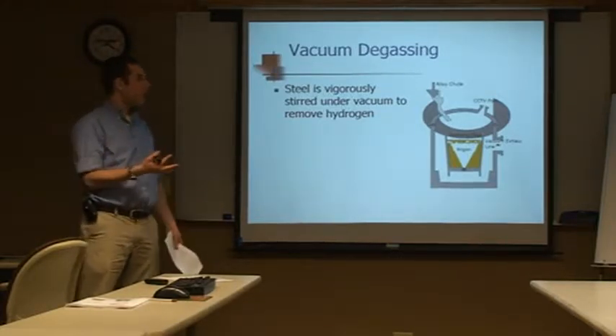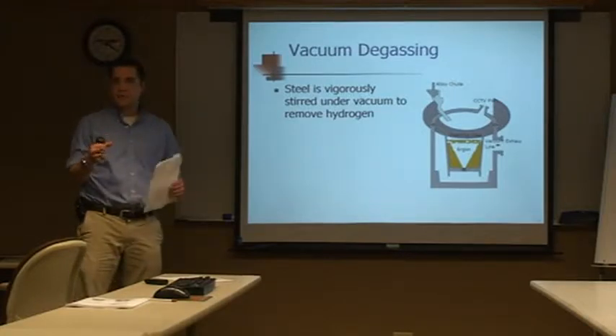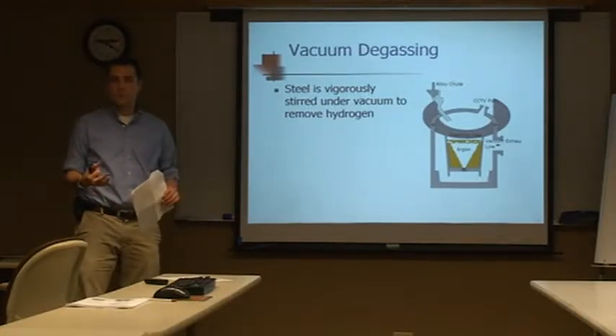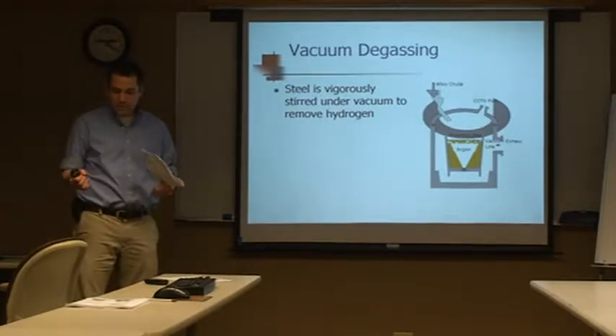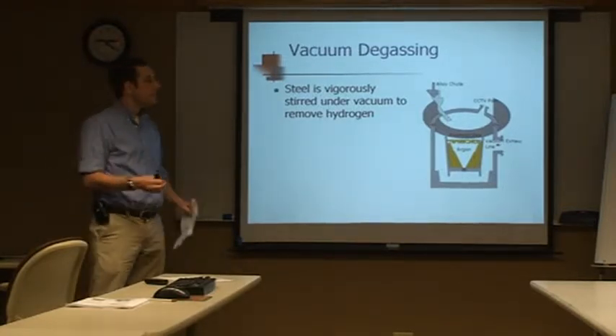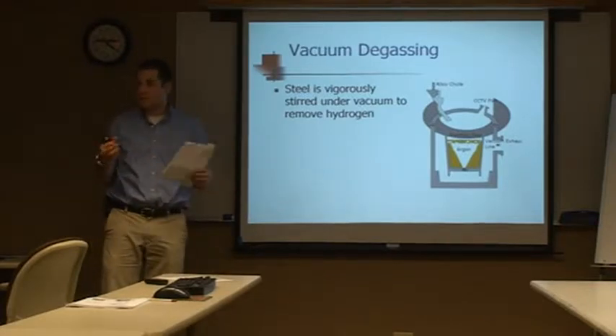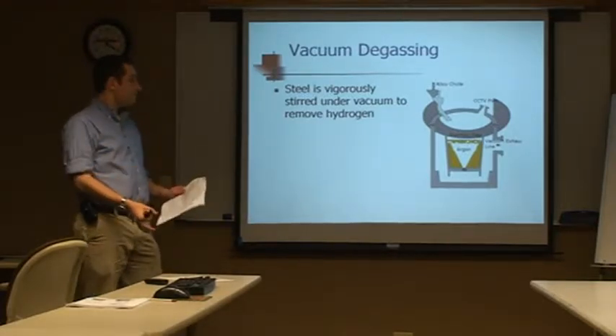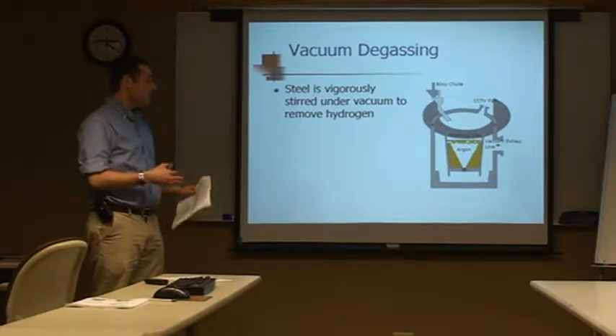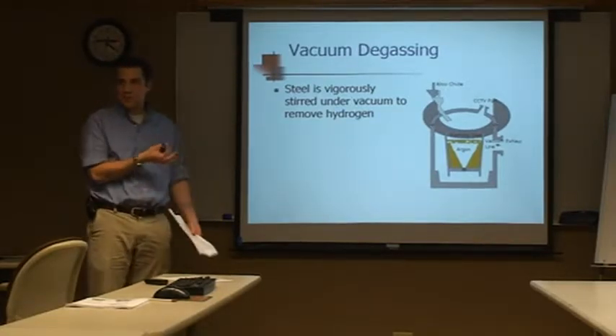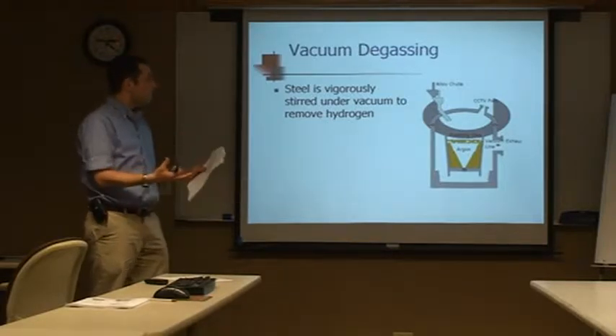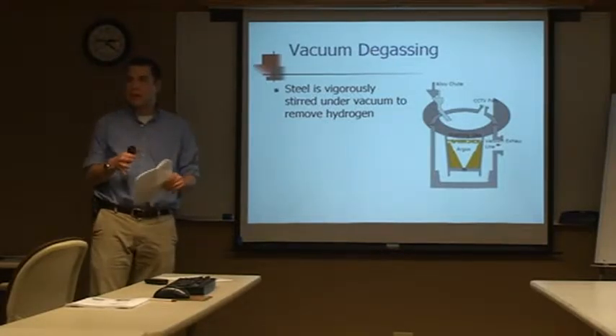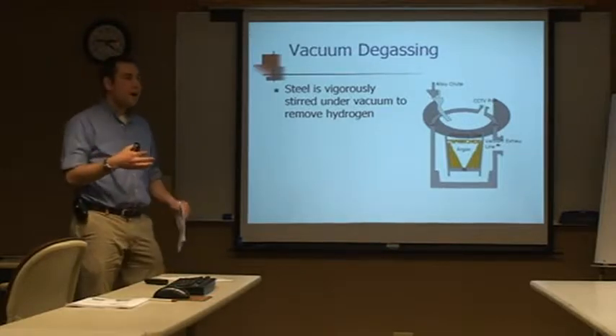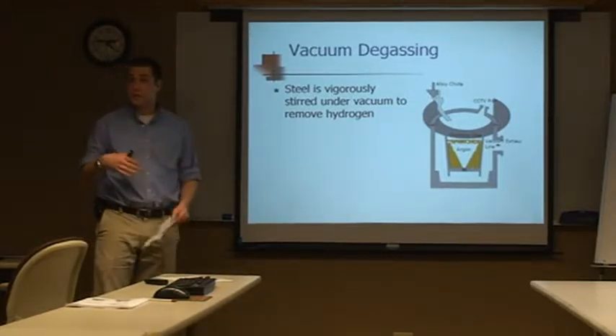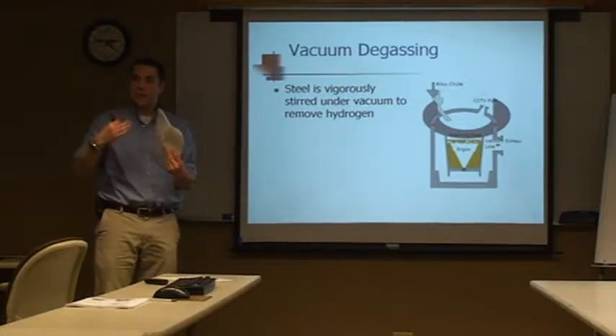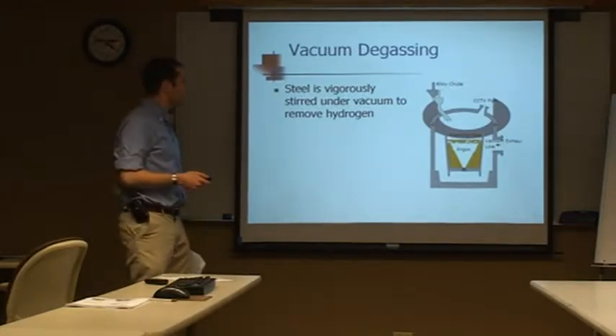It's kind of like if you had fine particles of dust in a carpet and you're trying to get it out with a broom or something like that. You could sweep all you want, but you just can't get to those little particles. So what you would do in that case is you use a vacuum to suck out the dust particles. And it's a little different because hydrogen's a gas rather than a solid, but that's effectively what we do. We put a lid over the ladle and draw a vacuum inside, and create a driving force for the hydrogen, which is a gas, to leave the steel bath and try and fill that space in the vacuum.